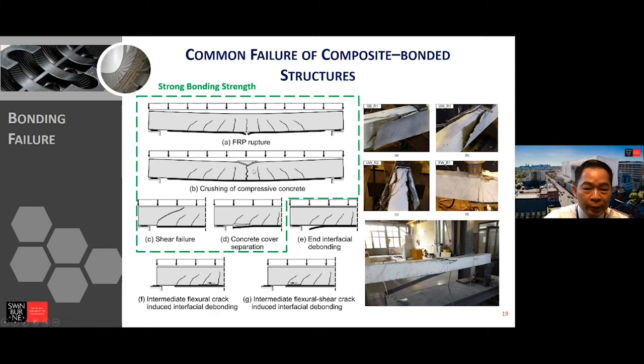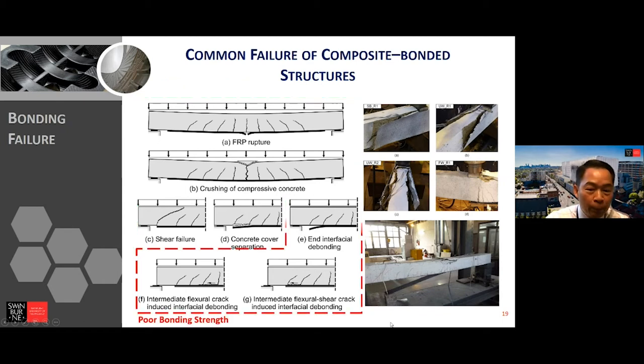this one is a good bonding, because the damage is basically in the composite itself. They are bonded very well. There are so many cracks on the surface of the concrete bar or beam. And in this failure, the composite hits very well with the concrete, and the crack is inside the concrete. It's good, but the poor bonding, like this one, we got the debonding.